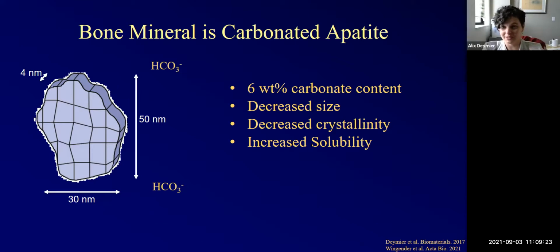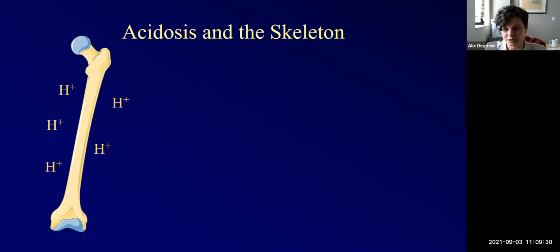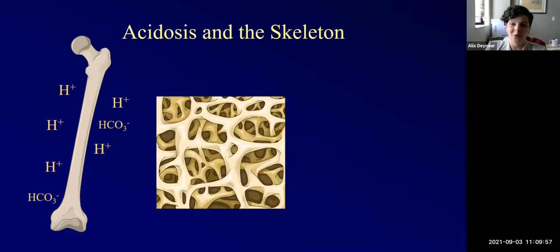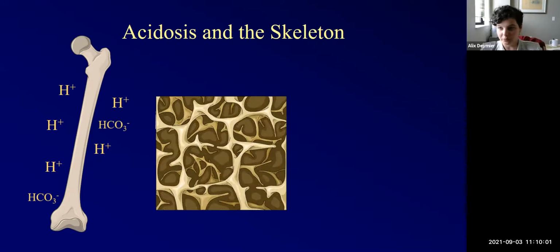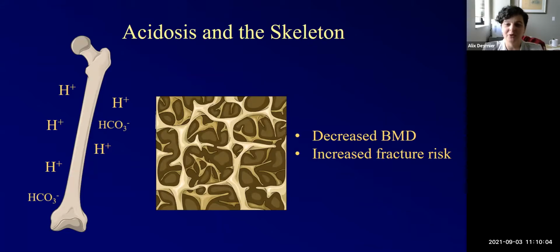Now that's a lot of material science, great, but what happens clinically? Well, clinically, we know that if you have a bone in your body, which we all do, you have your skeleton, when it comes into contact with acids, it releases bicarbonates and helps to neutralize the acid. And we actually see a lot of evidence that the skeleton helps to regulate the acid effectively and can bring people back into homeostasis. So you're thinking, great, fabulous. The problem is, in order to release that bicarbonate, you have to dissolve your bones. And that means that you go from having a normal bone structure to an osteoporotic bone structure. You have decreased bone mineral density and you get an increased fracture risk. So even though it's great in terms of bringing your pH back up, it's really bad in terms of bone health.